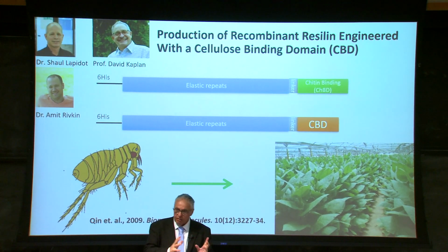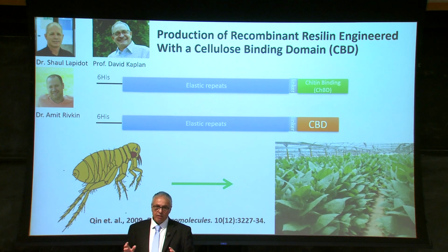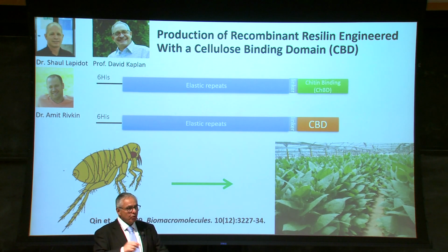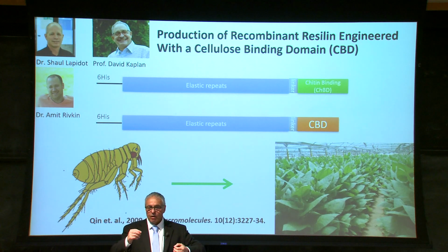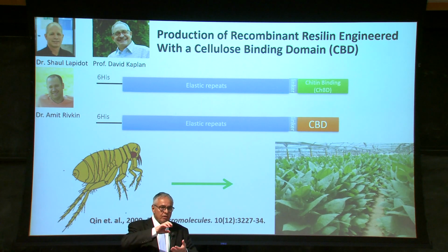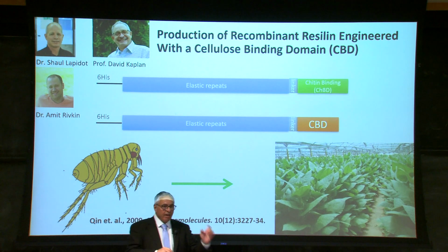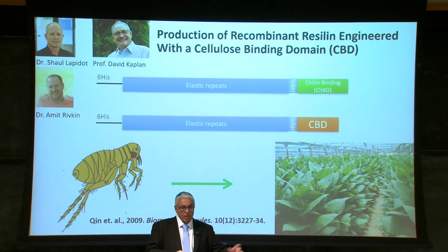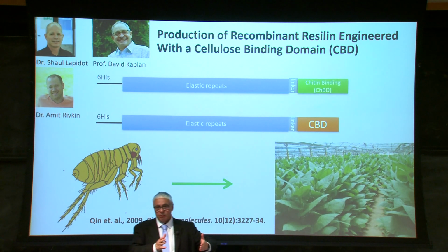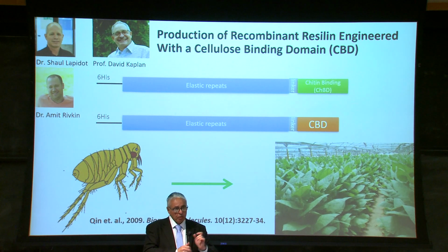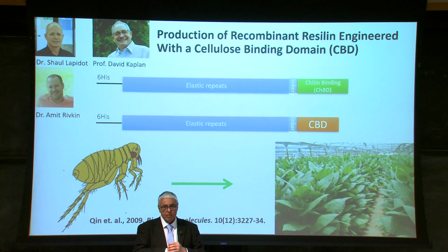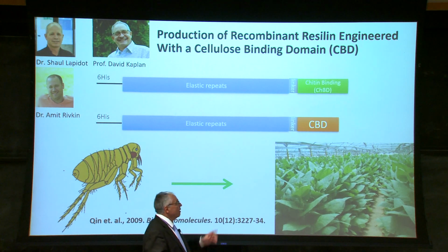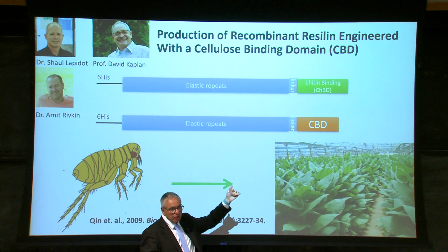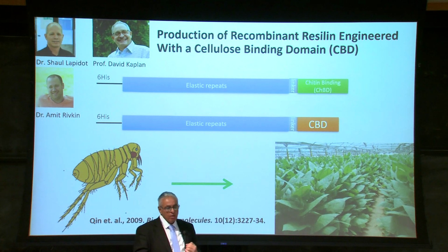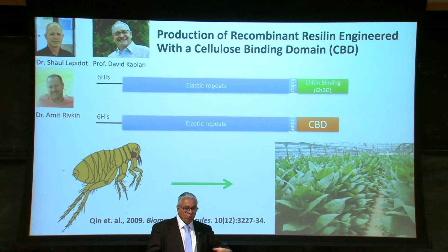But I didn't tell you the entire story. In fact, in nature, it's not just the resilin. Actually, it's a nanocomposite that is made of nanochitin fibers, where the resilin is attached to these nanofibers using a chitin binding domain. So you have the elastic region, and then you have the chitin binding domain. But we prefer cellulose for all the obvious reasons. So we simply replace the chitin binding domain with a cellulose binding domain. So now we have the opportunity to make composites with cellulose nanocrystals.